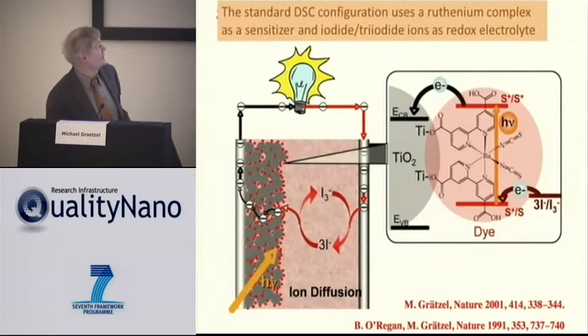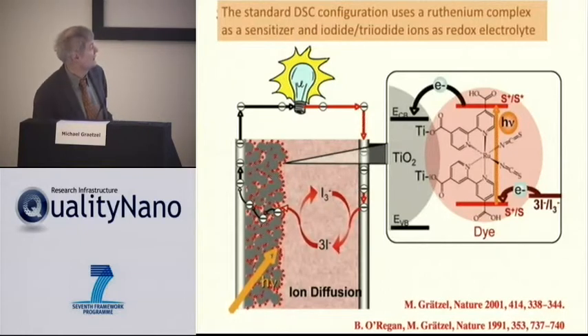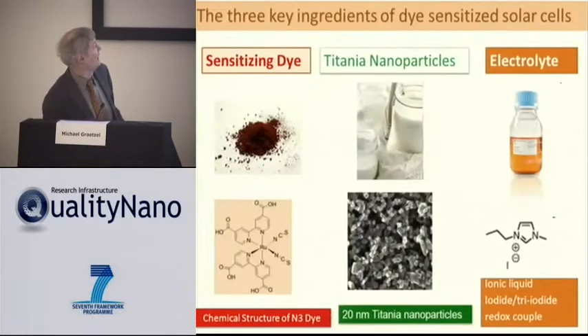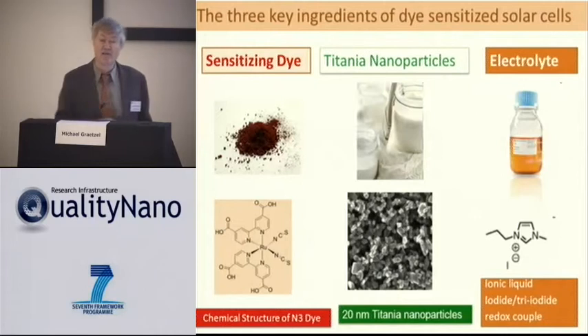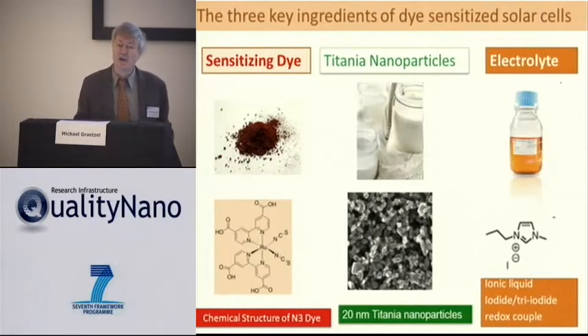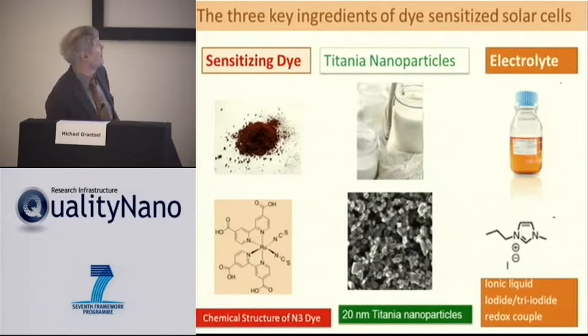So here's our standard. The ruthenium complex coordinates to the titanium ions, and we used iodide, triiodide. That's the standard composition. I show one more time here the dye structure. This dye actually has been very carefully examined, whether it's environmentally compatible. The biocompatibility tests have been performed and have shown it's actually harmless. It doesn't hurt the microorganisms.